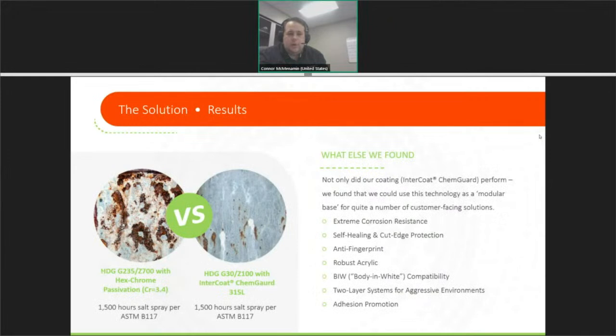To get into a little bit more detail, I show a photo on the left. This is a G235 or Z700, Z720 perhaps, with a hex chrome passivation on the left, compared against a Z100 or Z90, and then with the Intercoat ChemGuard 315 added on the right. We prep samples in our lab, both internally and send them out to external salt spray providers. This test was 1,500 hours to 10 to 15% red rust per one of the ASTM norms. And you can see, we haven't shown the whole panel, but you can see Intercoat ChemGuard is a very beefy, very robust corrosion inhibitor compared to some of the thickest zinc coatings that you can get on the market today.